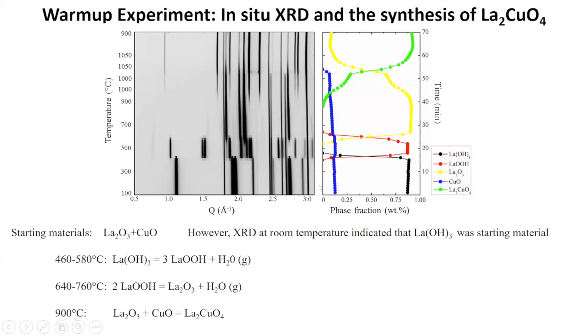So what's shown over here at the right-hand panel is the starting materials, which is the copper oxide in blue, and then that lanthanum hydroxide compound in black. You can see that that is suppressed at 400. The other lanthanum oxyhydroxide becomes available. That is displaced in turn. And the lanthanum 2 oxygen 3 is present in the stoichiometric quantities above, say, 600 degrees.